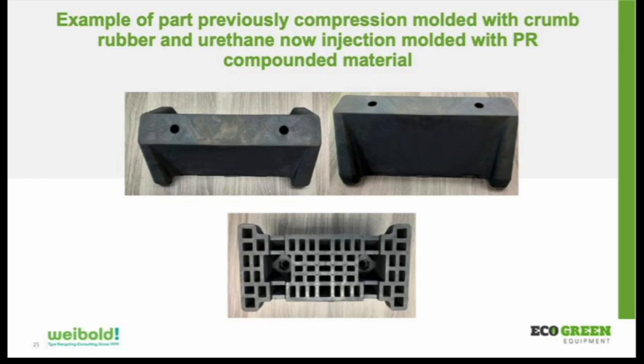It's a roof block. It's what you use if you have a flat roof and you're going to set air conditioners or piping, whatever, on top of a roof. This was a compression molded part that previously weighed about 5 pounds and had a break point of about 5,000 psi, or a load weight of about 5,000 psi. By converting it to an injection molded part, we were able to lighten the part to about 3 pounds.